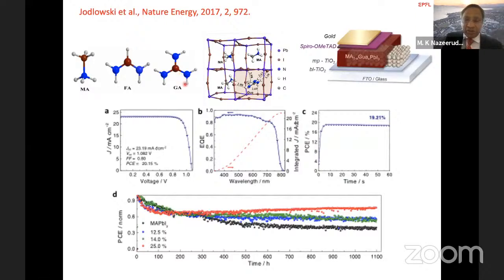But what we did was combine the smaller cations, 75%, with bigger cations, 25%, as shown in this cubic unit. So you have 75% of the smaller cation and just 25% of the bigger cation. They adjust into the cubic cell, and the cell configuration is shown here.